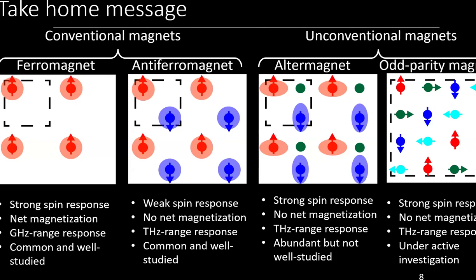So here, for ferromagnets, we know that it has a non-zero magnetization and we can manipulate that magnetization, which is relatively large compared to that in antiferromagnets. It couples to magnetic field. We can perform spin filtering. So a whole range of effects that is based on spin polarization of electrons is applicable here. For antiferromagnets, essentially bands are not spin split and they are degenerate, and you cannot construct spin filtering out of an antiferromagnet easily, for example. So many of the effects that rely on spin polarization just don't work with antiferromagnets. That's what I mean by weak spin response.